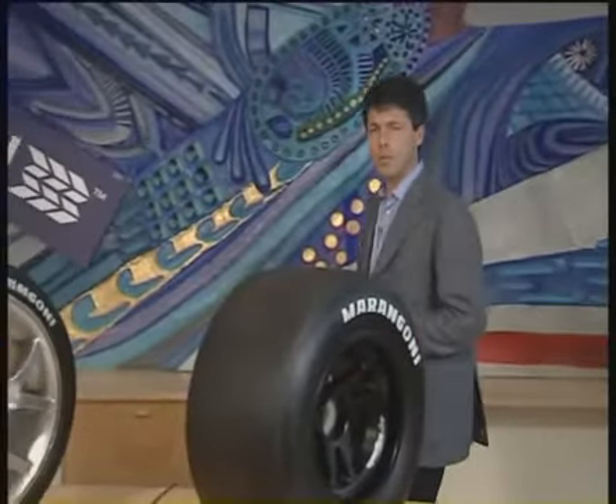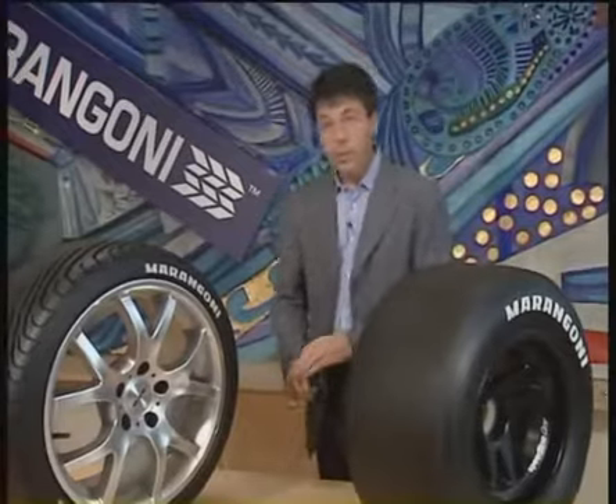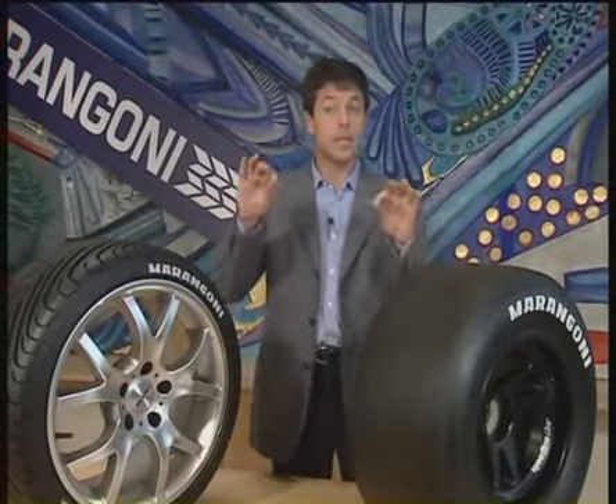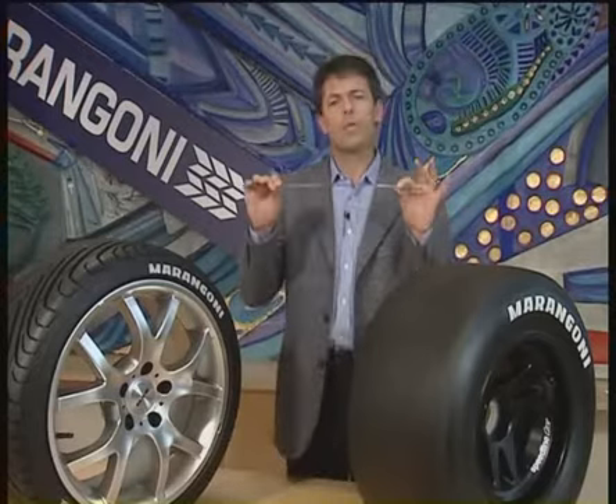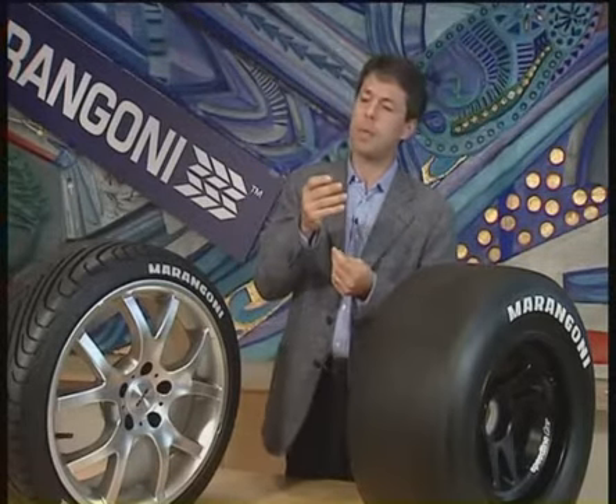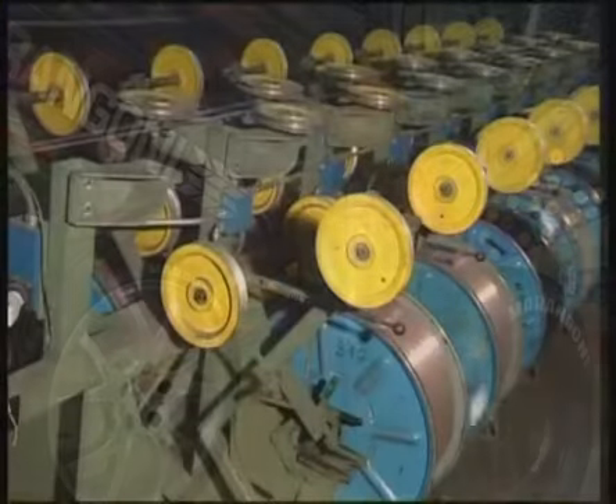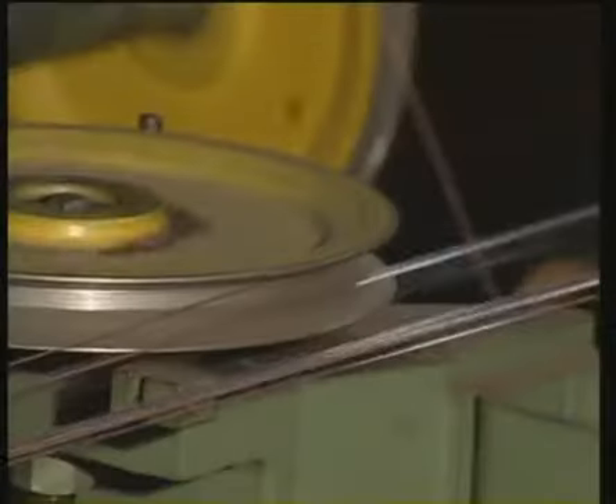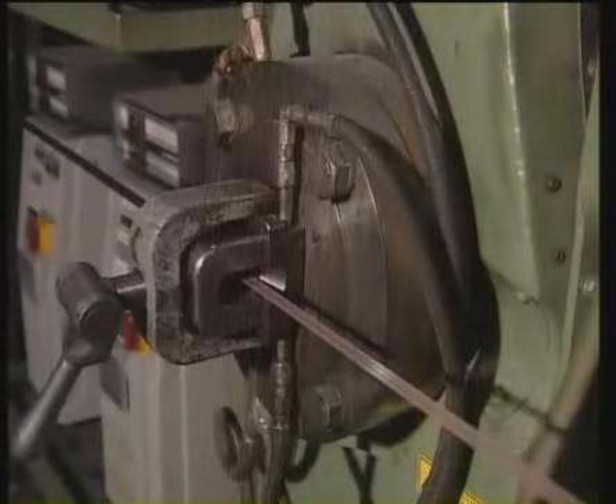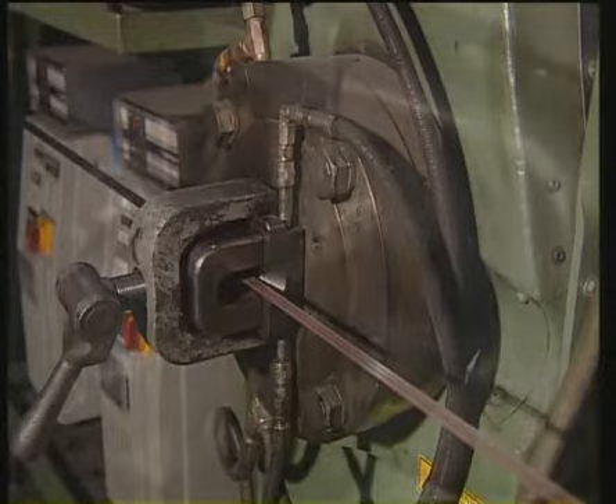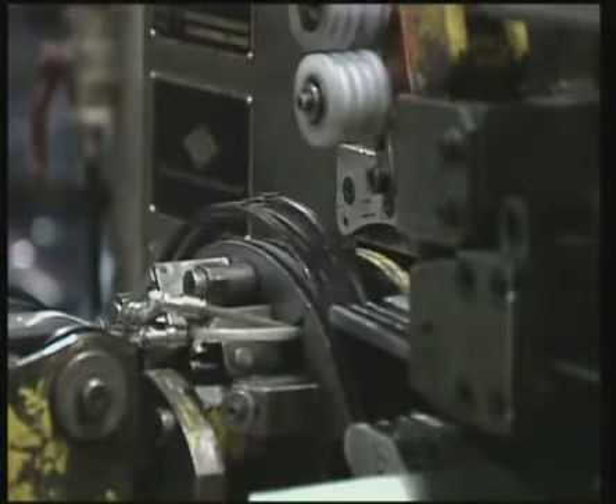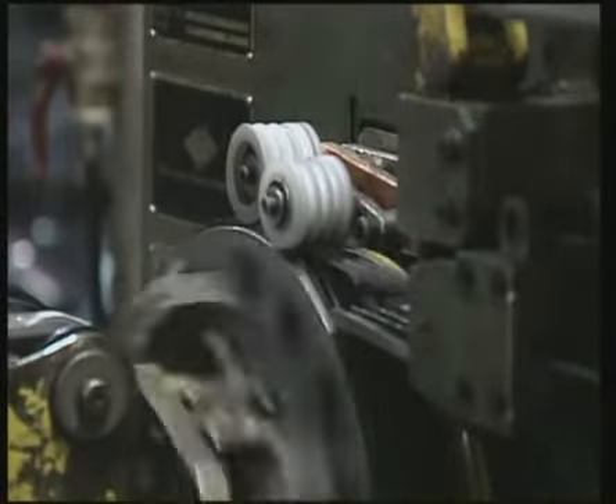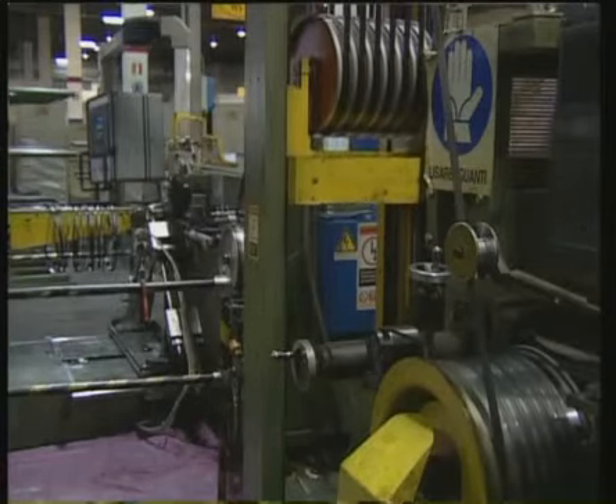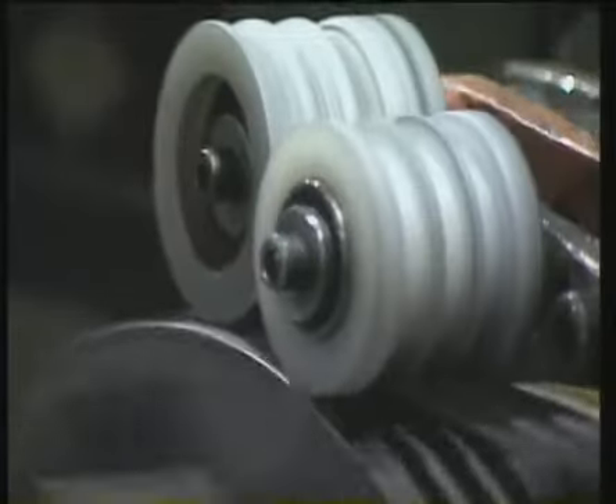Let's go through the steps of the manufacturing process, starting with the reels of steel wire coated with copper to improve adhesion to rubber. A certain number of wires, which varies in relation to the size of the tire, are grouped together, impregnated with rubber and wound on a spiral with a number of turns that also varies depending on the size of the tire. When using this technology, no welding is required. In fact, the adhesiveness of the rubber that impregnates the wires guarantees the stability and the non-deformability of the spiral until the curing phase.